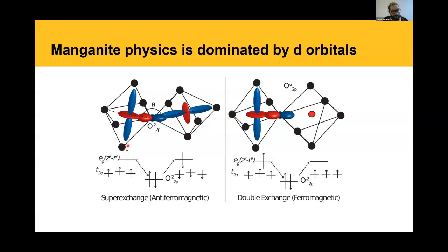This exchange interaction is at several eV energy, so it's much larger than the temperature. On the other hand, the tunneling interaction, essentially the hopping interaction between these 2 orbitals, is on the same order as the Jahn-Teller distortion. In this case you have equally occupied orbitals, so you don't get a Jahn-Teller distortion. But if you have another Eg orbital, which I haven't drawn here, which is unequally occupied, that gives you this Jahn-Teller distortion. And the Jahn-Teller distortion is on the same order of energy as this hopping interaction.